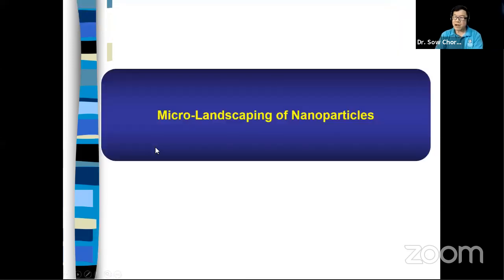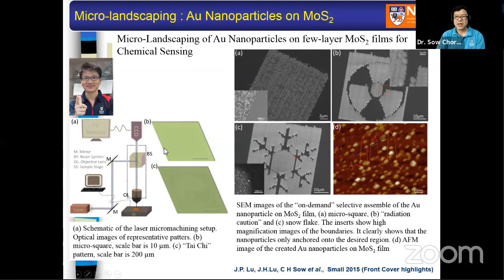Yeah, okay. So now with this focused laser beam patterning, I'll show you the kind of things you can do. Micro landscaping of nanoparticles, okay? So here is the idea. We play with molybdenum disulfide, MoS2. So imagine you take a piece of molybdenum disulfide, you take the focused laser beam and come in, and then you focus and you describe a certain pattern. What you may do is actually break up the bonds in the MoS2. You may have dangling sulfur in a particular pattern with the micro patterning. Then you finish patterning, you take this MoS2 sample out with the pattern, with all this dangling sulfur bond created by the laser beam.